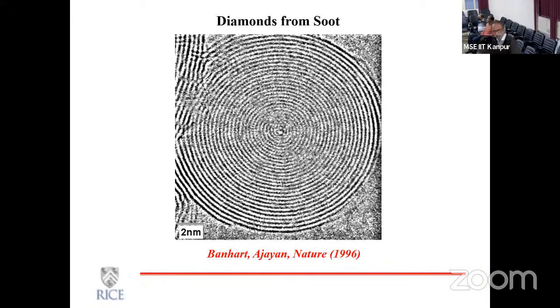Typically, people have looked at transforming materials using an electron beam. So you take carbon, you hit it with the electron beam, and it forms graphitized structures. That's understood. But what we did, without really knowing it, was an irradiation experiment at a higher temperature. There was a heating stage, so we just wanted to try it. But when you did this at higher temperature, what you see is a very strange metastable structure. In fact, if you look at the actual separation between layers in graphite, it is decreasing as you go toward the inside of the structure, which means that the material is getting compressed to the core.